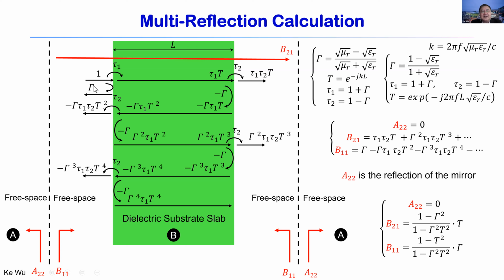The multi-reflection calculation is based on the physical phenomena here. For example, if one wave comes here, it will first of all encounter the first interface. This boundary condition can be characterized by tau 1, and part of the wave will reflect back, and part of the energy will be transmitted into the material under test. Then it will encounter the second interface from material to air, and will reflect back here again. Part of the energy will continue to propagate. So this reflection continues to reflect back, going through the second reflection and also transmission. So you can see reflection, transmission, reflection, transmission. So that is the multi-reflection calculation here.